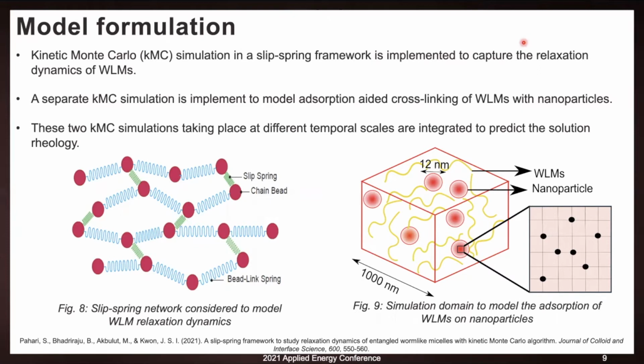the system. Kinetic Monte Carlo algorithm, which has successfully been applied to many studies related to polymer stress relaxation, is utilized here. Alongside relaxation dynamics, adsorption of worm-like micelles on nanoparticles has been considered in this framework. Specifically, adsorption of worm-like micelles on nanoparticles has been modeled with a separate KMC simulation. Finally, since the KMC simulations for relaxation dynamics and adsorption take place at a very different time scale, a novel integration strategy is implemented to integrate these simulations and predict the solution rheology.